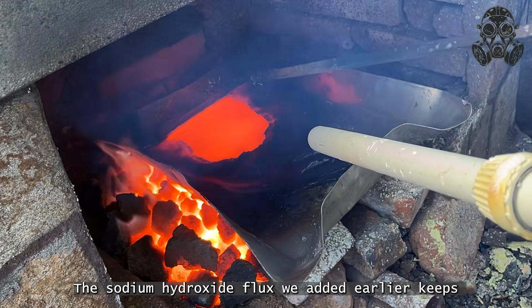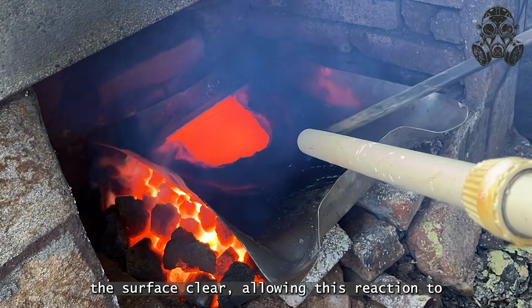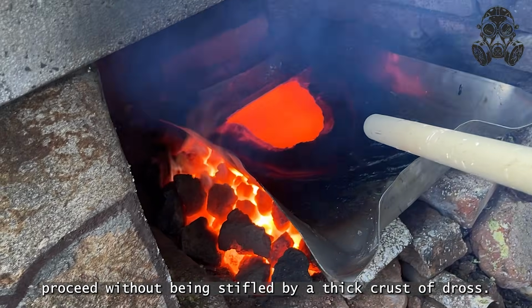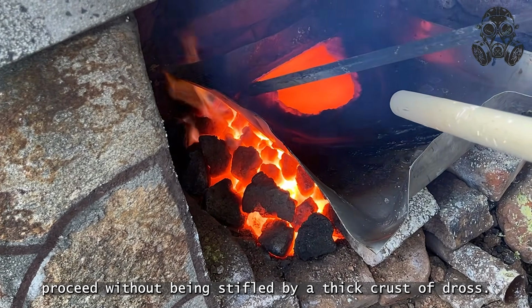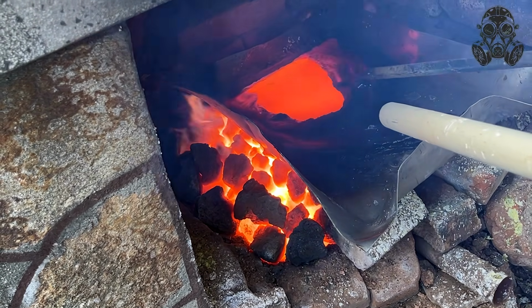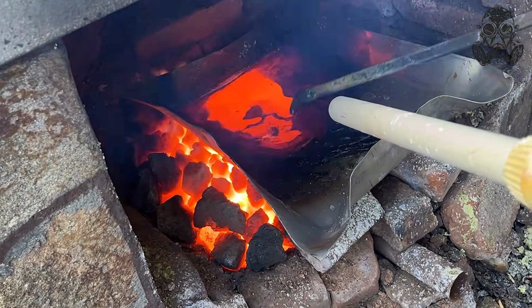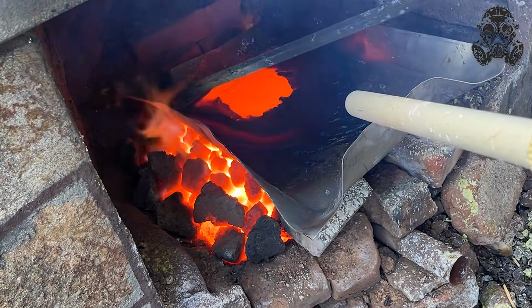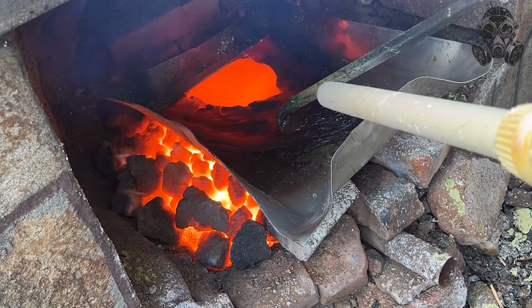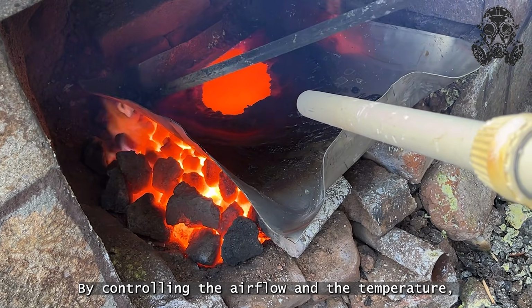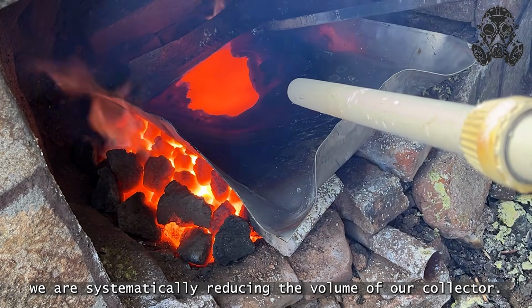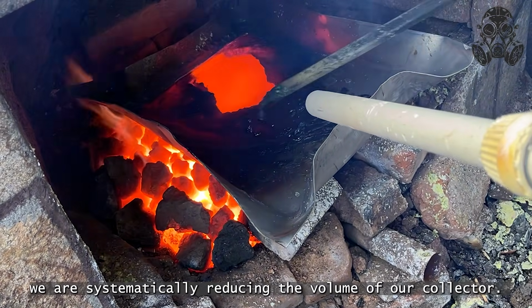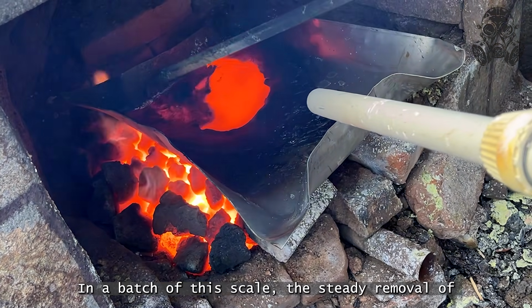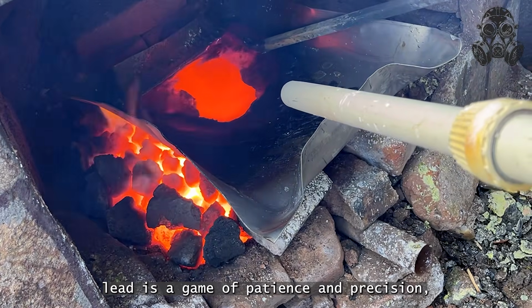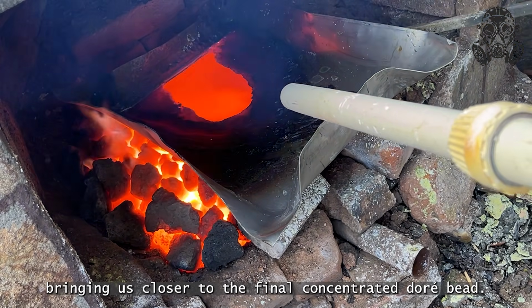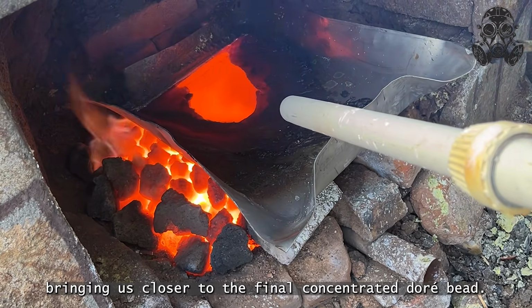The sodium hydroxide flux we added earlier keeps the surface clear, allowing this reaction to proceed without being stifled by a thick crust of dross. By controlling the airflow and the temperature, we are systematically reducing the volume of our collector. In a batch of this scale, the steady removal of lead is a game of patience and precision, bringing us closer to the final concentrated doré bead.